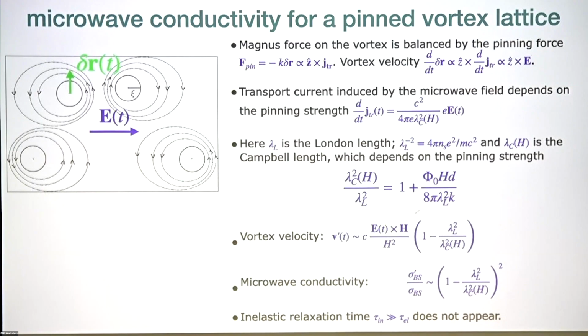And then in this analysis, what you find is that the velocity induced by the microwave field is the flux flow velocity reduced by this factor of the ratio of the London and Campbell length. Okay, and as a result, what you find is that the microwave conductivity in the Bardeen-Stephen mechanism, which we call sigma Bardeen-Stephen prime, its ratio to the flux flow conductivity is this factor, which depends on the pinning strength and the magnetic field. And again, the inelastic time does not appear when this happens.